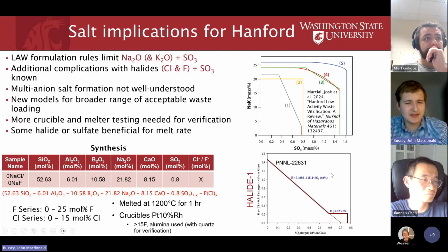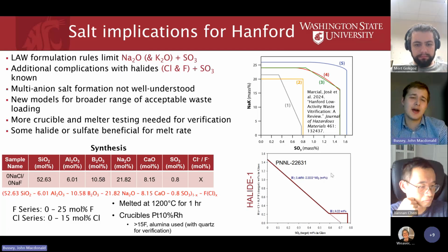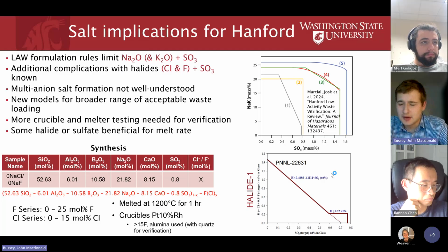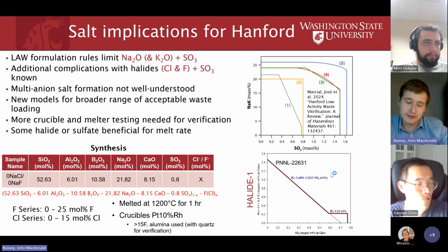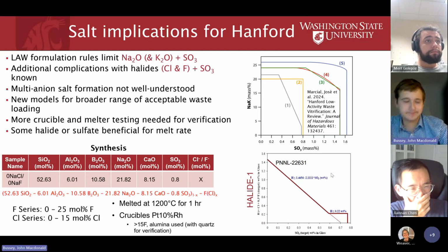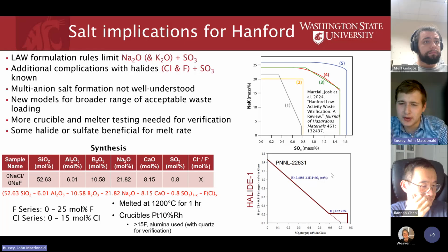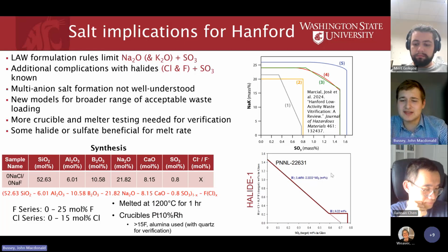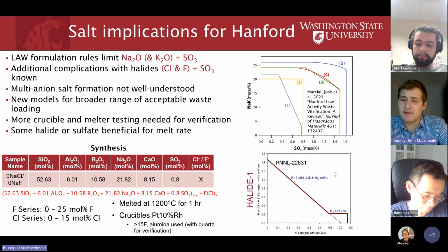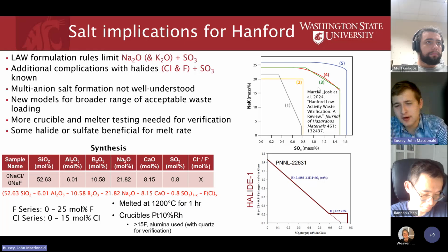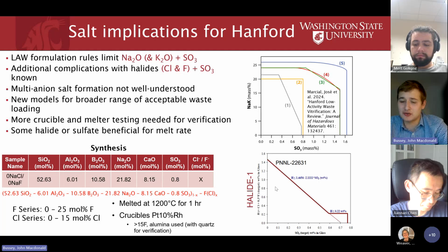But the interactions between different kinds of salts are not very well understood. A variety of models have been developed to encourage acceptance of higher waste loadings of salt, because some of these tanks contain significant portions of salt. And if you're limited in the amount of fluorine or chlorine or sulfate incorporation, that's problematic. As a ballpark, generally around 0.8% sulfate is the limit of the older models, although newer models have pushed that up to double. And for the halides, the range for chlorine and fluorine is much lower.